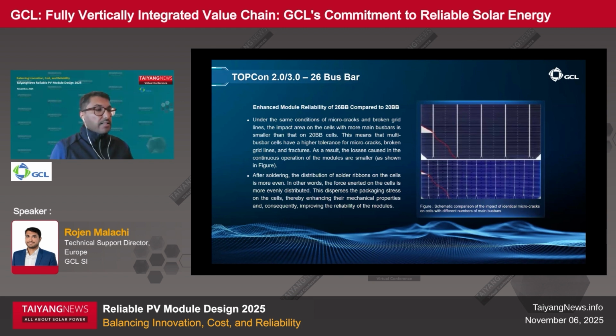This slide highlights the reliability improvements achieved in our TOPCon 2.0 and 3.0 using 26 bus bars compared to the traditional or the newest generation of 20 bus bar designs. First, under identical conditions of microcracks and broken grid lines, cells with more bus bars experience a smaller impact area. This means the 26 bus bar cells have a higher tolerance for microcracks and fractures, reducing performance losses during module operation. Second, after soldering, the stress distribution on the cells is more uniform.